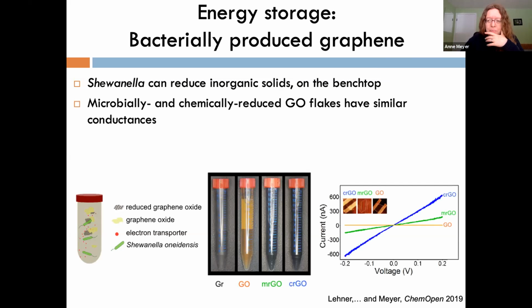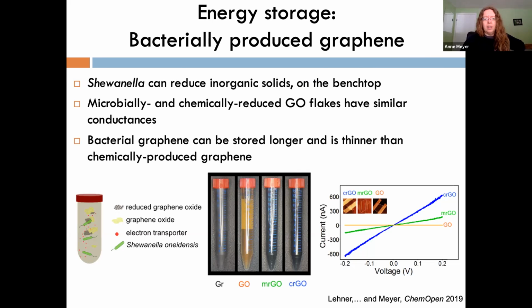And when we measure the conductive properties of these materials, it is with this kind of graph we're showing here on the right side. So the steeper the slope of this curve is, the more conductance our material shows. You can see in orange that the graphene oxide is flat, it's not conductive, it's an insulator. But then you can see the blue and the green curves have a high slope, right? And so in green, the microbially produced graphene is the same order of magnitude of conductance as in blue with a chemically produced graphene material. So we have quite good conductance with our microbial approach.